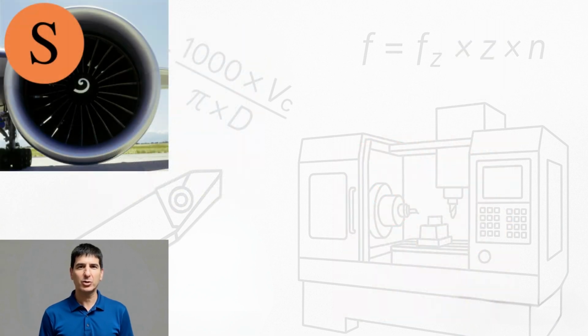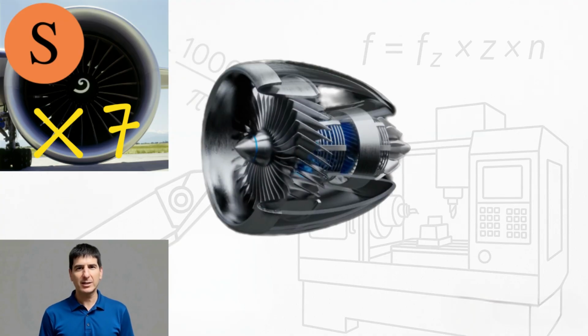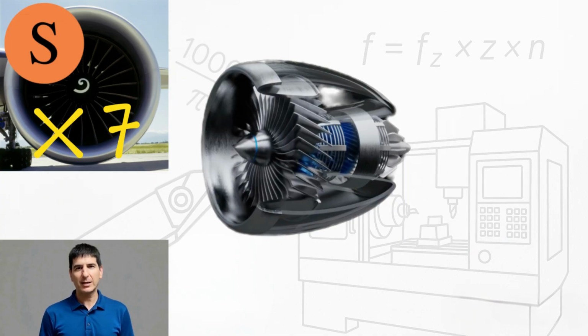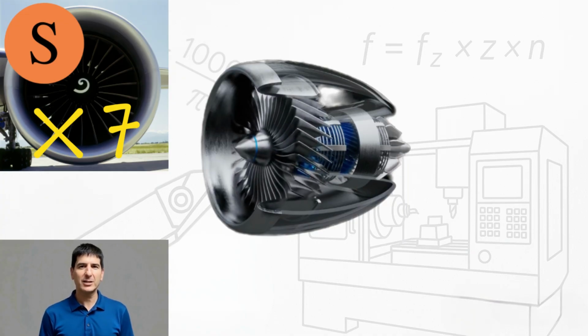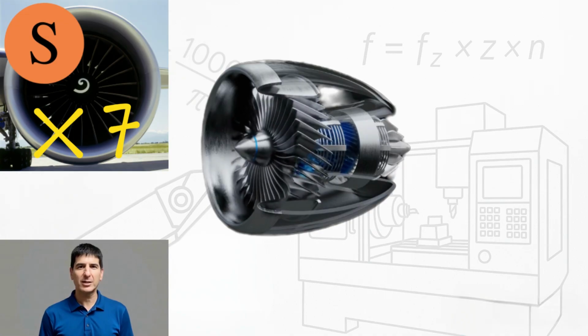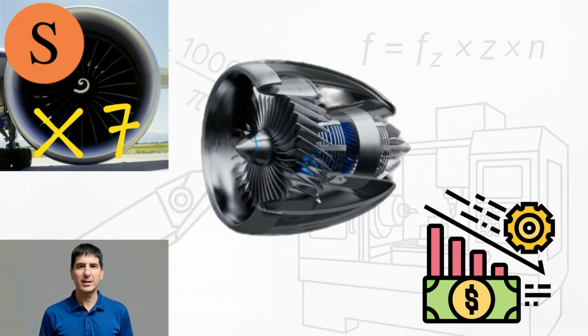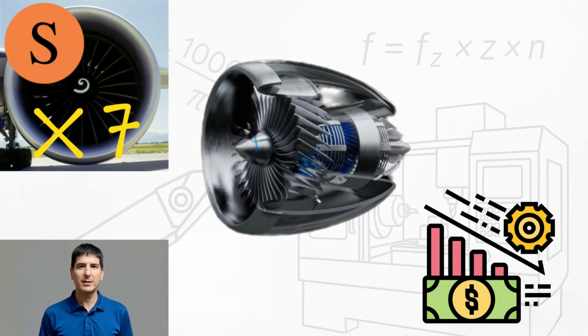But where ceramics truly dominate is machining nickel-based superalloys, like Inconel 718, where it can run up to 7 times faster than carbide. Some of these aerospace components are of considerable size, and can take hours to complete. In such cases, this speed increase translates to massive cost savings that dwarf the higher insert price.